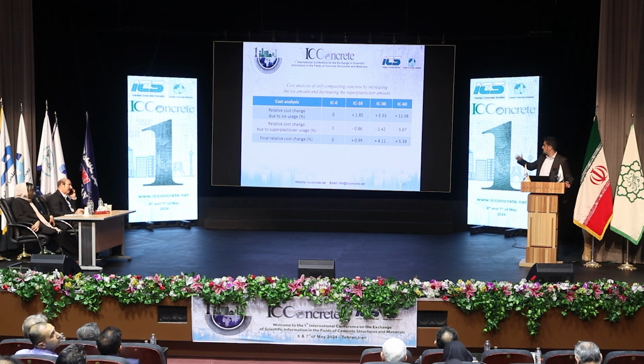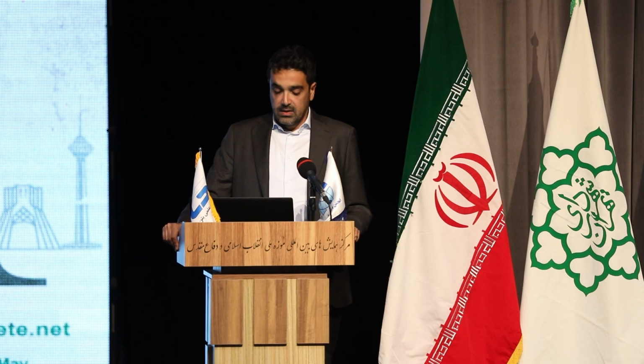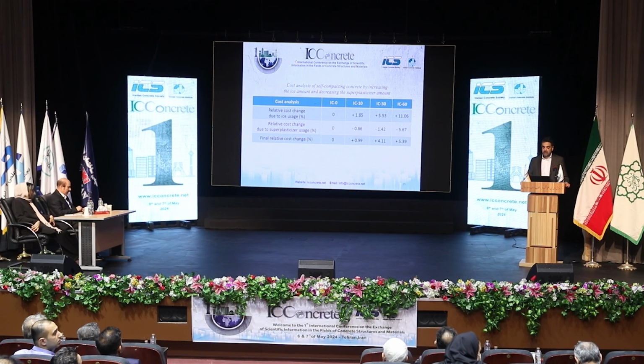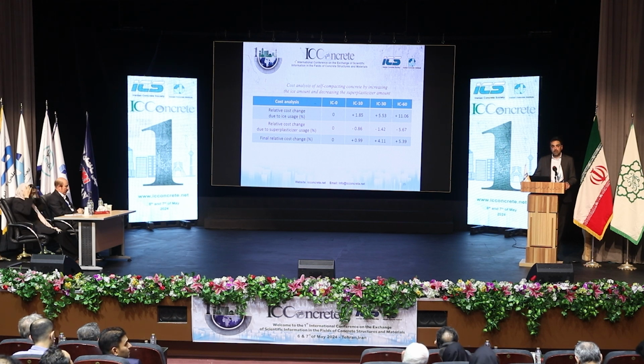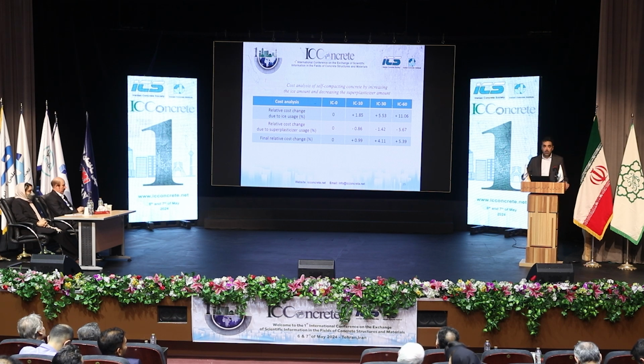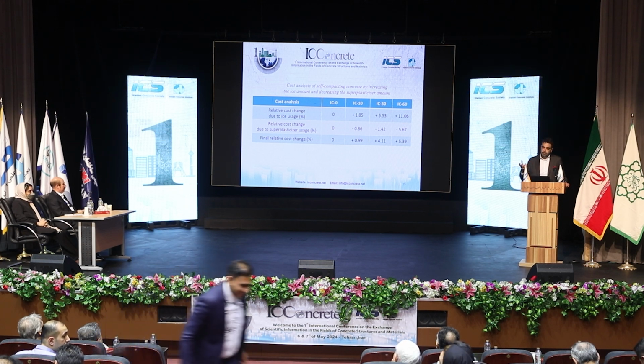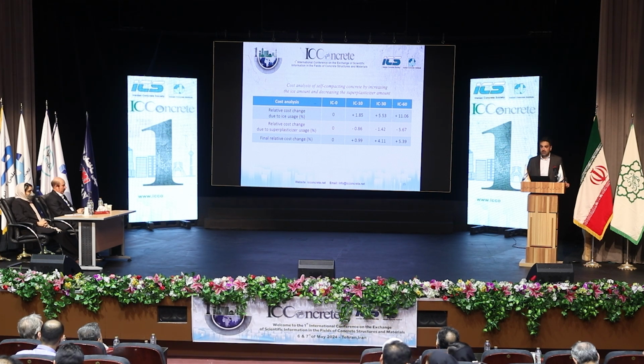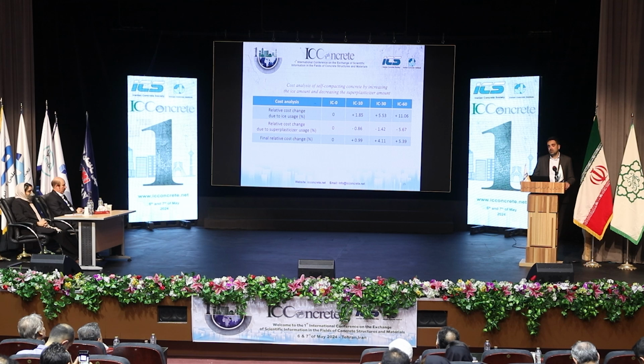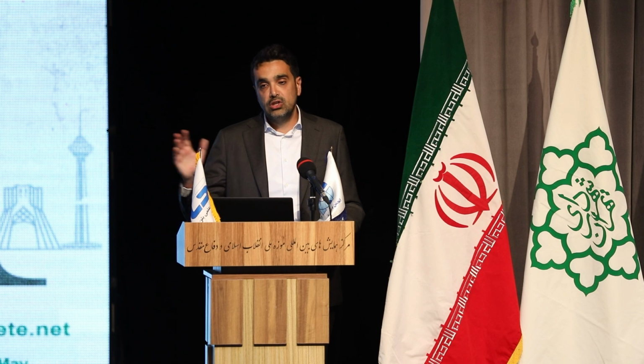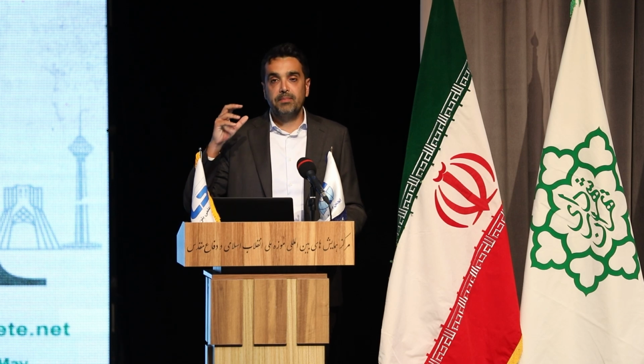As you can see in this table, in the first row, the relative cost of change due to ice usage increased, and because of using lower amount of superplasticizer, the cost of concrete decreased. But totally, the price of the concrete increased, but it was so limited. But the advantage of using crushed ice was using lower superplasticizer at job site, which is not such practical.